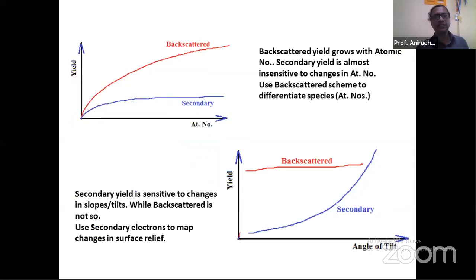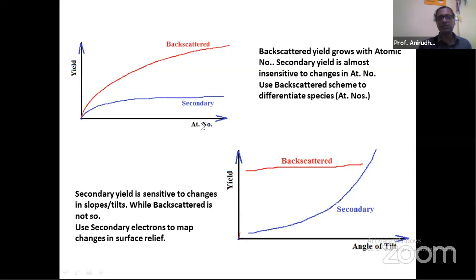Now, if you see this, this is how the yield from a backscattered scheme would depend on the atomic number of the species material. So you see that the backscattered yield would change according to different species, different target materials, while the secondary electron stream does not depend so much on the atomic species in question. Though there is a dependence, that dependence is weak. So therefore, you can use your backscattered packet to differentiate between different atomic numbers. Or in other words, you can use information from your backscattered energy to differentiate between two different materials, A and B, their distribution, at least on the surface.